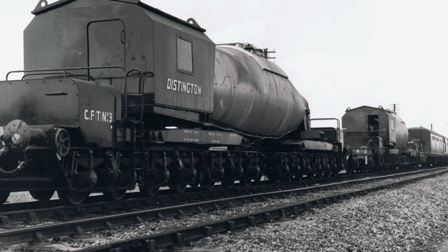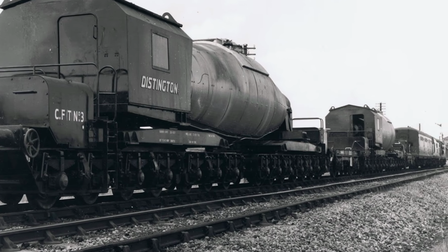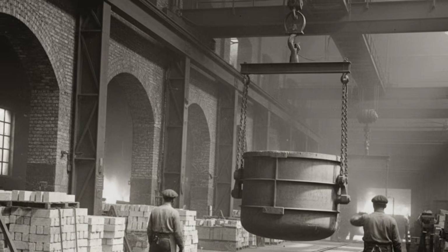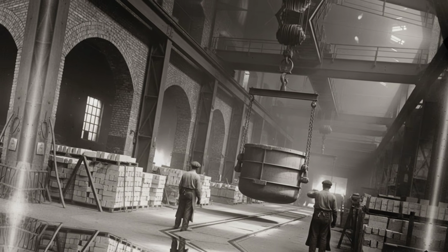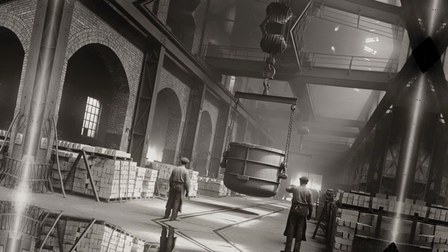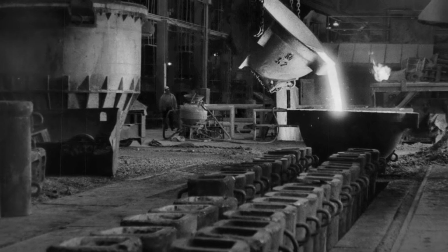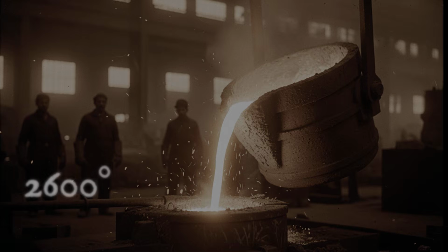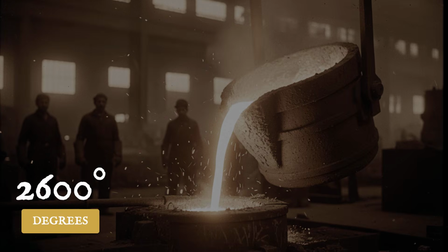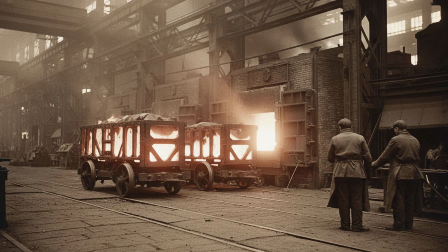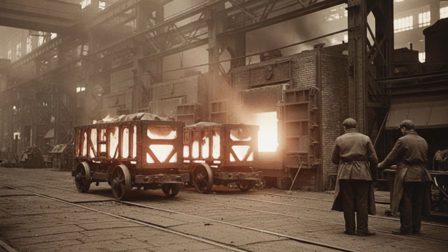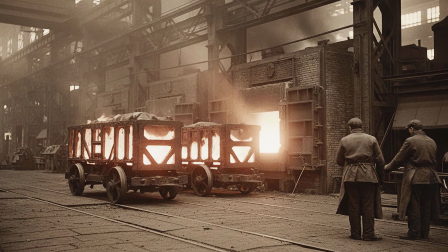Molten pig iron arrived from the blast furnaces in submarine-shaped railroad cars, refractory-lined vessels that looked exactly as they sound, which were brought directly into the shop and tipped by crane to pour the iron charge through the furnace doors. The iron arrived at roughly 2,600 degrees Fahrenheit, which meant the car carrying it to the furnace door was itself radiating heat across the shop floor.